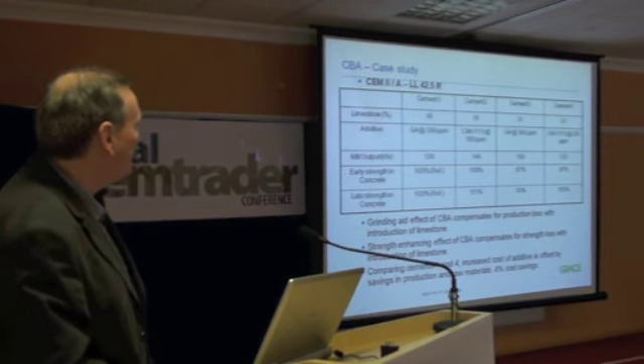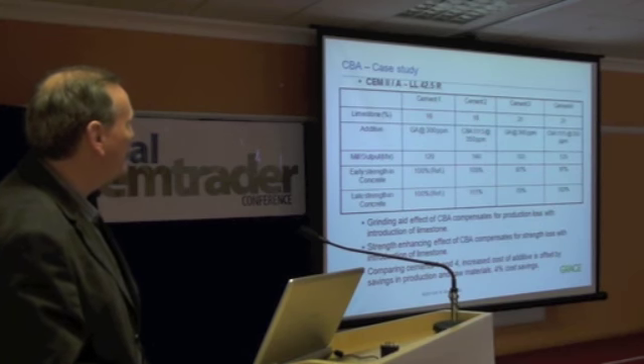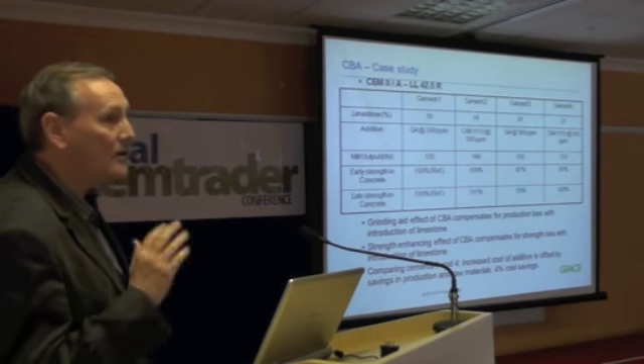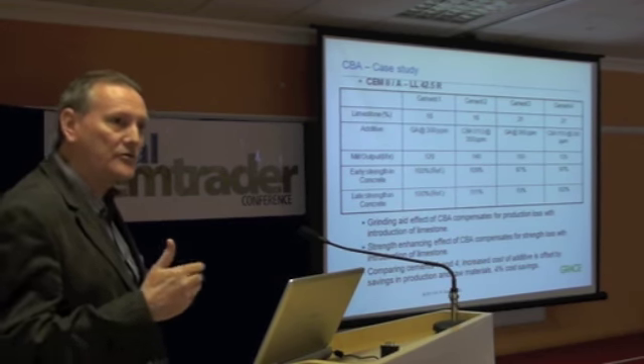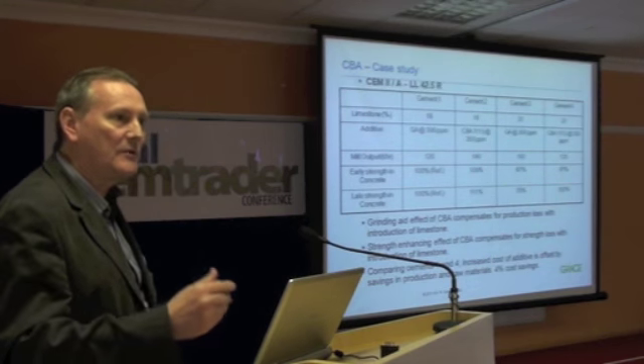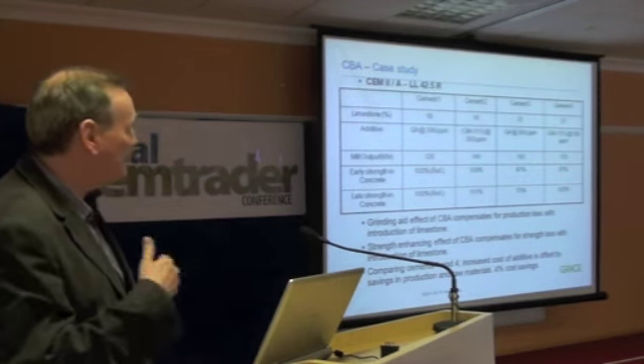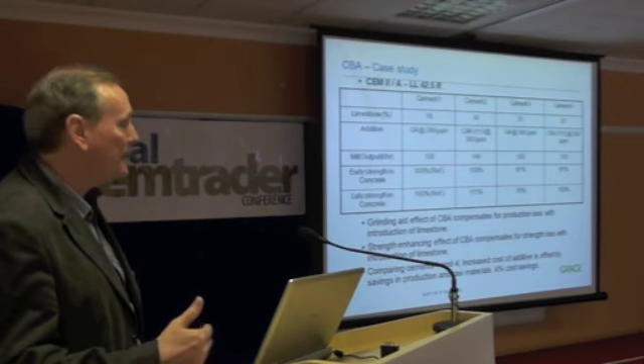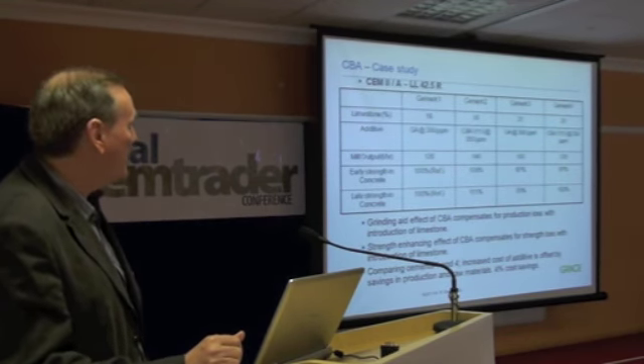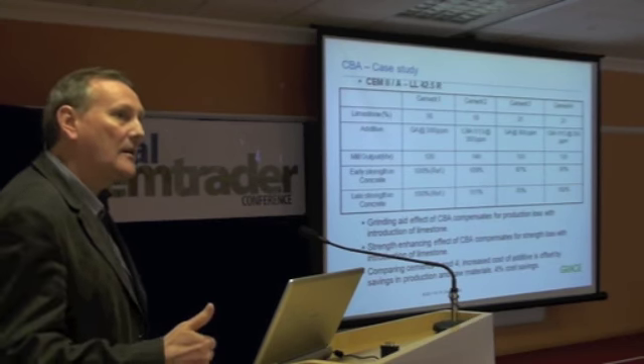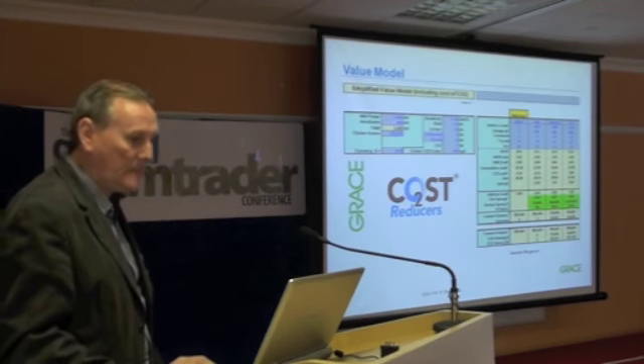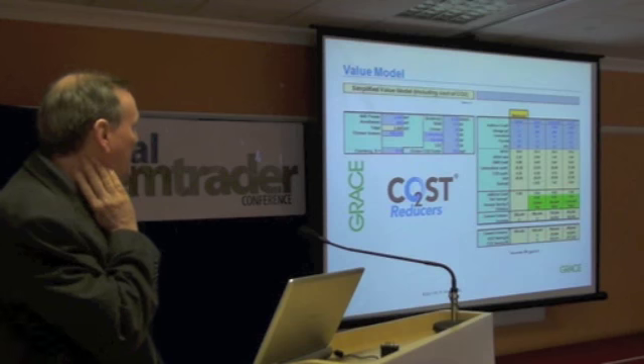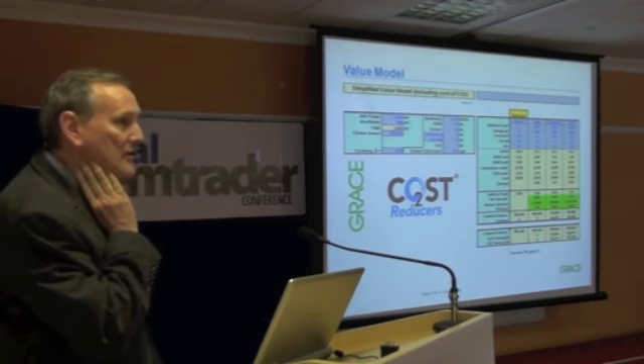So here we see the ability to achieve a 5% increase in limestone in cases 3 and 4, or in case 4, just comparing to a regular grinding aid. A regular grinding aid is something that's neutral to the cement performance but affects the process performance, whereas the CBA in this case is a quality improver that enhances the cement performance and allows you to maintain the strength level and put in 5% more limestone, which would be a cost saving to the cement producer. And it's quite simple to do a value model of looking at the benefits.